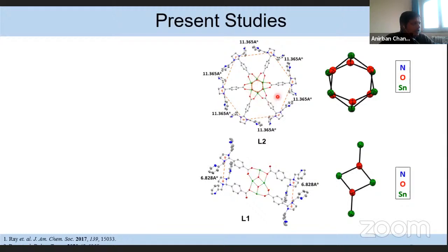one, L2, which is containing the hexanuclear stannoxane core with 6 tin centers and 6 oxygen centers, and it forms a drum-shaped molecule. From the crystal structure of this molecule, it is evident that for the hexanuclear system, all these metal binding sites are equally distant from each other, and the distance is around 11 angstrom. Whereas for the tetranuclear system, out of the four, only two centers are close together, at approximately 7 angstrom distance.